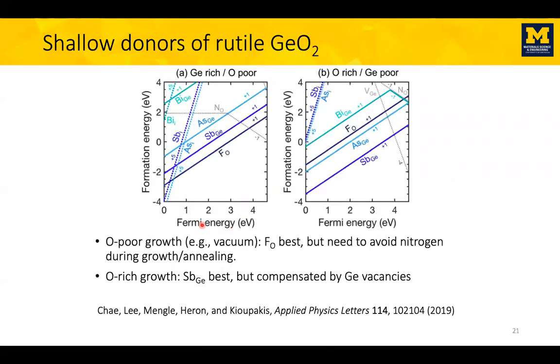So the first thing we'll look at is donors in germanium oxide. So here again, you see the formation energy of various kinds of defects as a function of the Fermi level between the top of the valence band and the bottom of the conduction band under germanium-rich or oxygen-rich conditions. And we find that if you grow under oxygen poor conditions, it's easy to remove oxygen atoms and replace them with a fluorine. And this fluorine atom will always be positive no matter what the Fermi level, meaning it is a donor. It gave its electron to the conduction band.